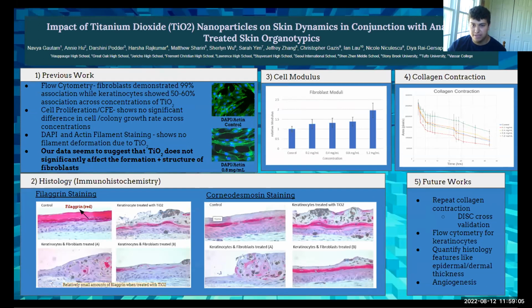So titanium dioxide is used in a number of cosmetic products, but the small size of titanium nanoparticles can lead to penetration of the skin. We wanted to observe the impact of titanium dioxide on skin. So in order to do this, we grew skin-equivalent organotypics and treated them with titanium dioxide.